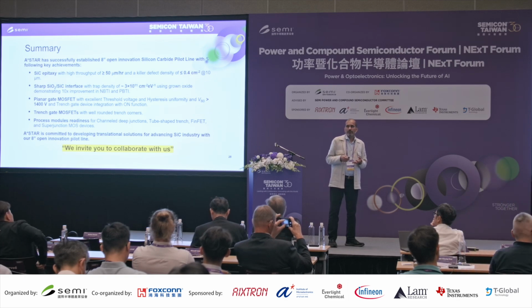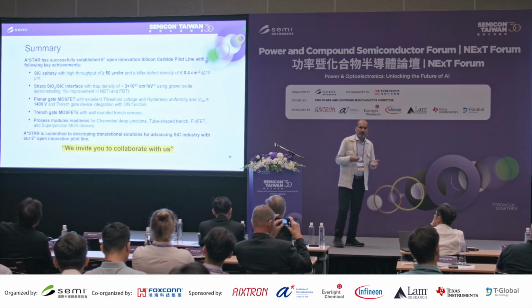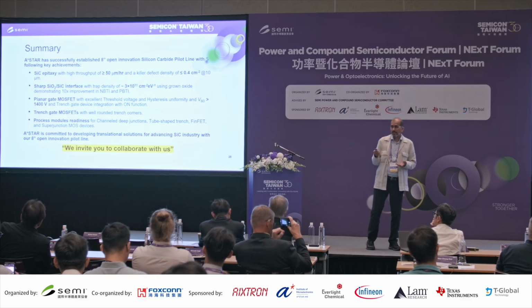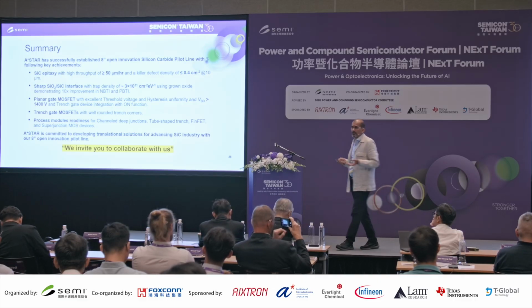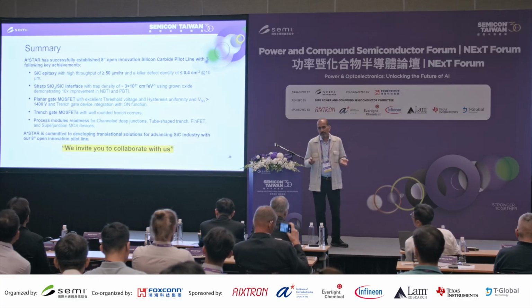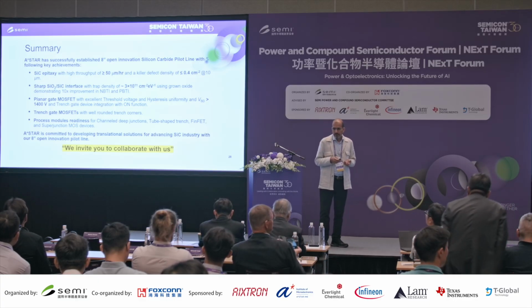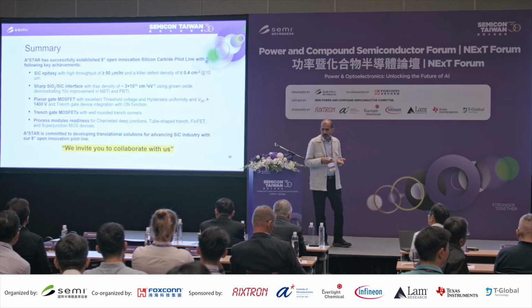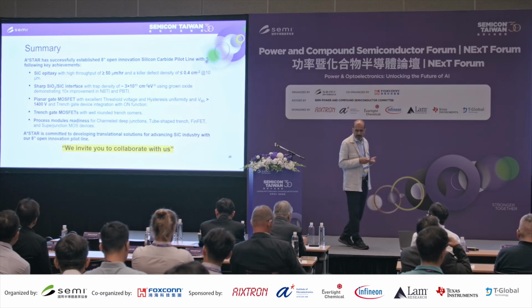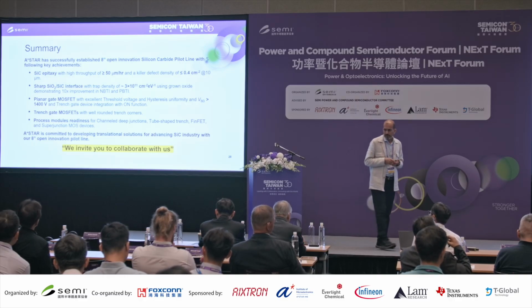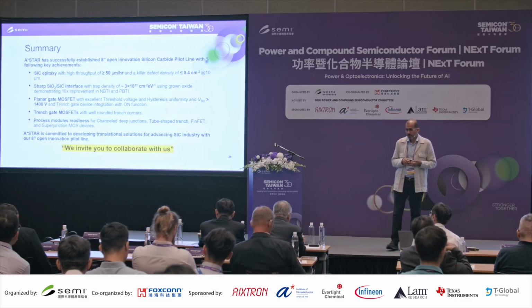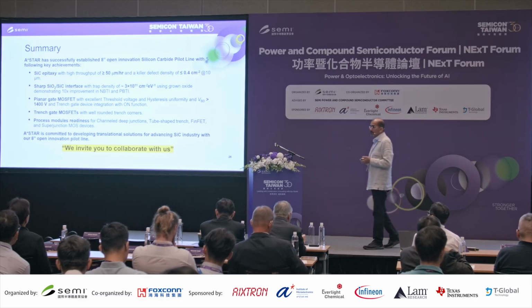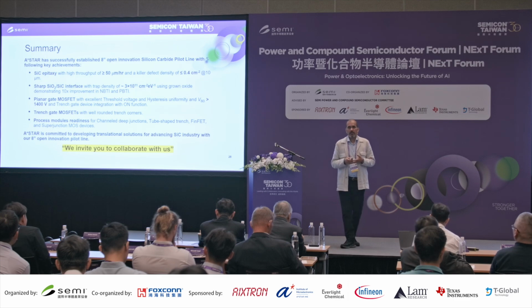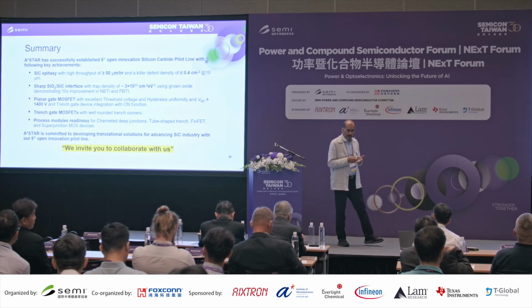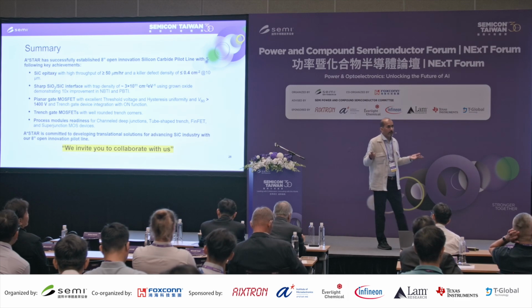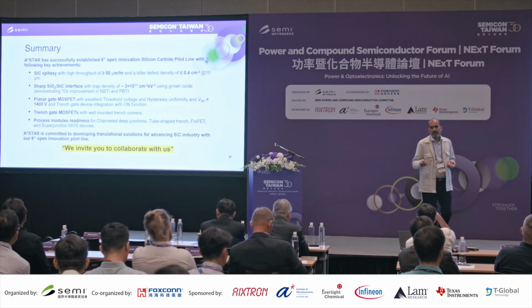So this is not only for 1200 volts, but tomorrow if we are driving to very high voltage, this epitaxy can grow very low defect material up to 100 micron very easily. It's a single wafer chamber. We have good MOS interface. We have demonstrated planar devices, trench devices, and process module for future devices, FinFET, and super junctions. That way we are ready with the platform to have deeper engagement with industry. We already have it, but we invite you all to work with us in silicon carbide. Thank you very much.